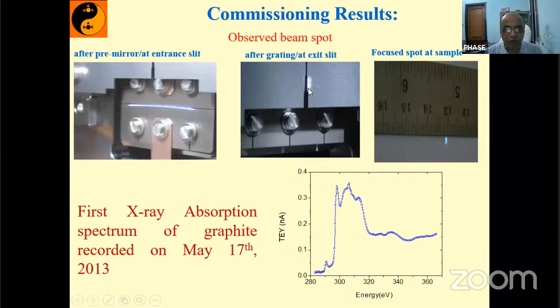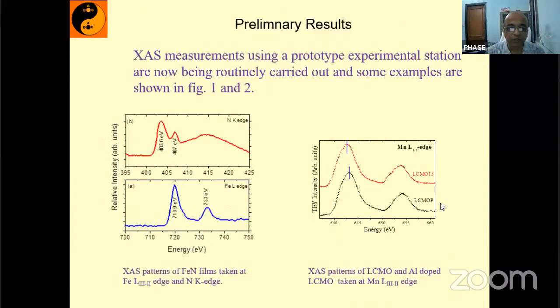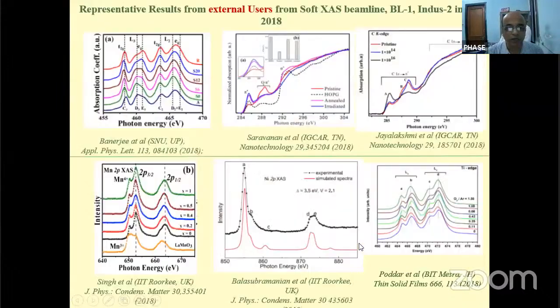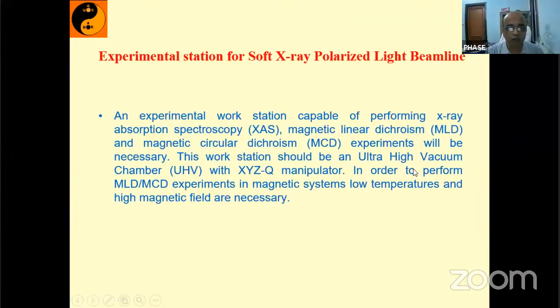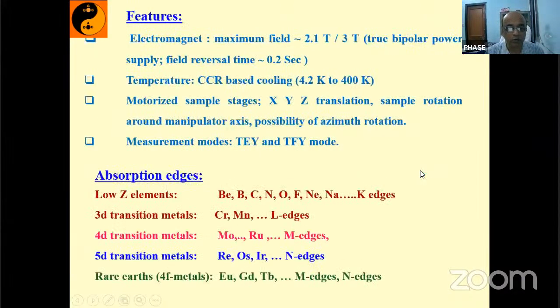This is the final beam on the sample. You can see the beam at the exit slit, and this is on the sample. So a very fine beam is there, and a very small sample is necessary to do the measurement. And then these are some preliminary results of the normal absorption experiment. When you select the beam from the center, you get the normal absorption experiment, and a lot of people have used it for normal absorption studies. But I will show you what is new, that is, magnetic measurement.